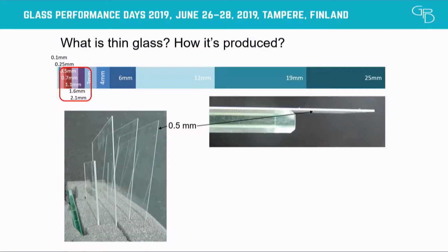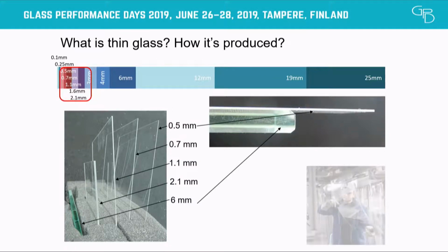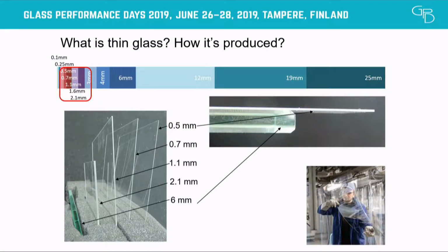So what is thin glass? Well, in the way we consider thin glass, we talk about a glass that goes from 0.5 millimeters to 2.1 millimeters. And here, just to give you an idea visually, what 0.5 means compared to a 6 millimeter glass and all the other thicknesses. And if you ever had the chance to touch it, it's quite impressive, and it's very interesting. But what is the problem? Normally, up to now, most thin glass is produced either by the overflow process or the down draw process. And this makes it a sort of expensive process. So in AGC, we started to say, OK, what can we do to make it cheaper? I will come back to this later.